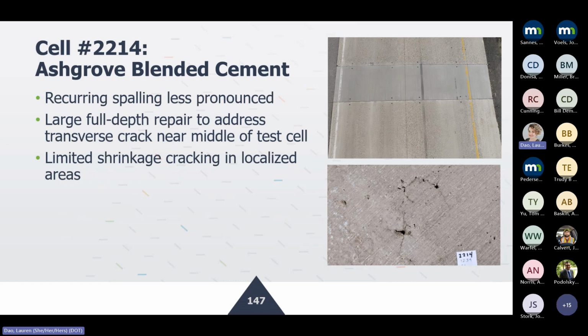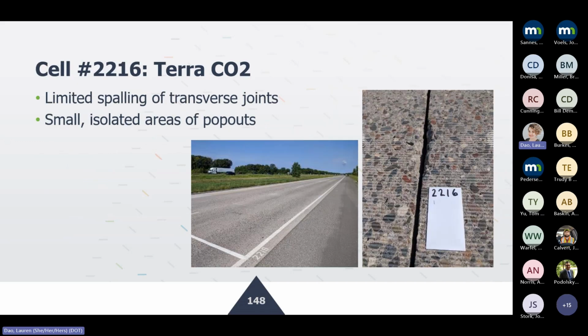And then the Ashgrove blended cement, again, the recurring spalling that we saw throughout the length of all the test cells was less pronounced in this particular cell. But then there was a large full depth repair. I believe that was because of a transverse crack near the middle of the test cell. And then we also saw some localized areas of shrinkage cracking.